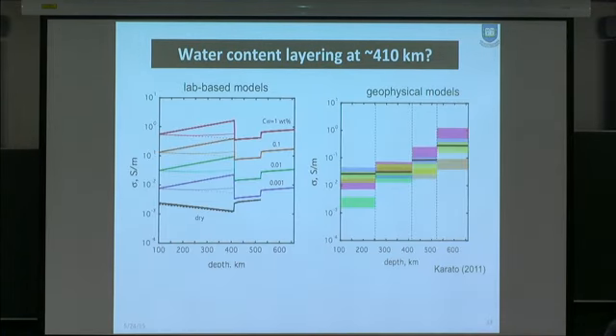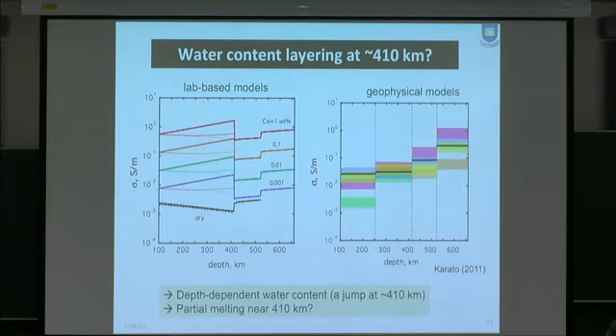And also, in terms of electrical conductivity, if you look at the global plots, you can see a substantial increase in conductivity at transition zone depths, as opposed to what you expect from laboratory data for constant water content. If you assume constant water content, like 0.01 for green, conductivity must drop at the 410 boundary. But the observation shows a jump, which means, in my view, there's a jump in water content. So that is my interpretation of the conductivity profile, which might be the result of partial melting near 410 kilometers.